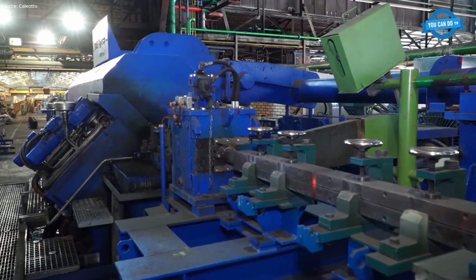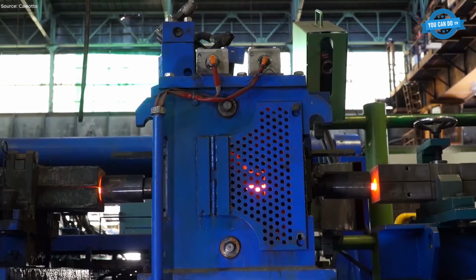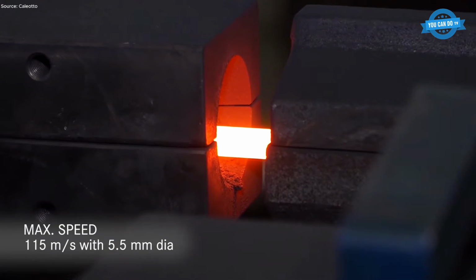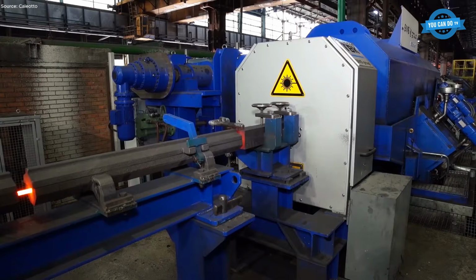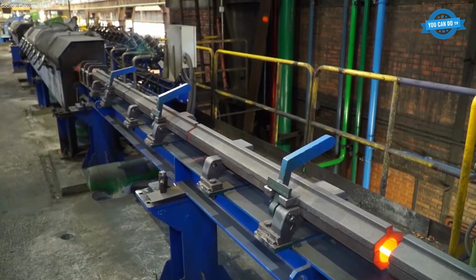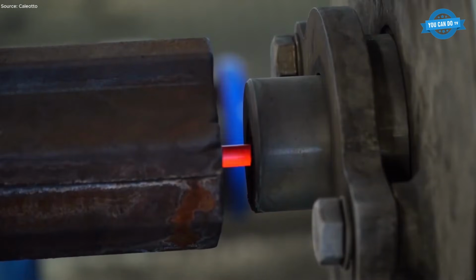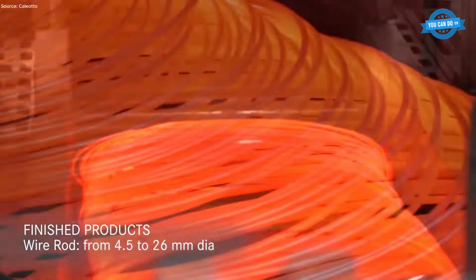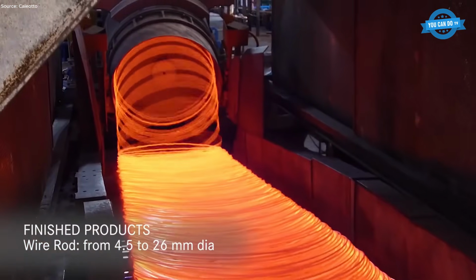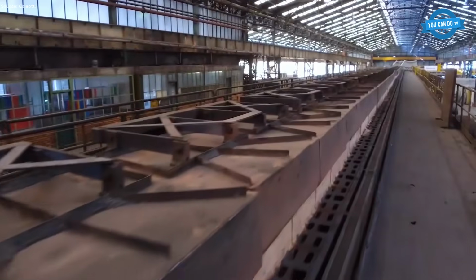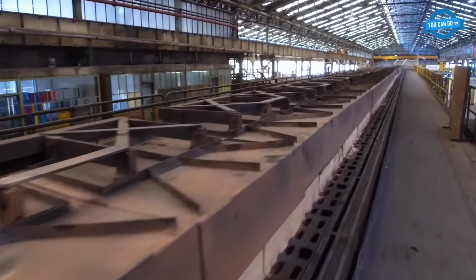Standard rolling covers diameters from 4.5 to 26 millimeters, while the newly implemented loop enables thermomechanical rolling between 13 and 26 millimeters, enhancing mechanical properties through controlled deformation and temperature management. The MEER Drive Plus system, combined with a 4-pass sizing block, guarantees dimensional precision and surface quality.